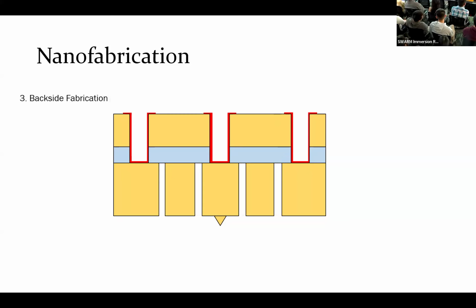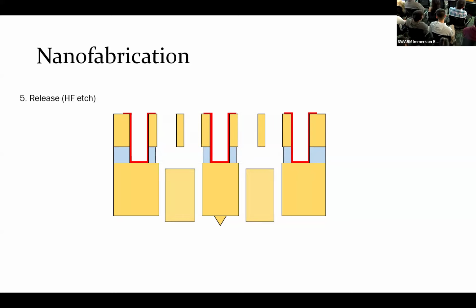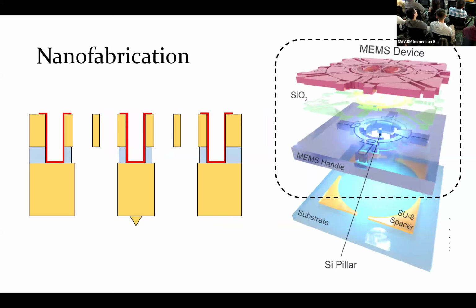And then we do the Bosch etching from the backside and also the top side, and then we release it using vapor HF. These constitute the different layers as you see here, the device layer and the handle layer, and how the silicon pillar in the middle is used for putting down the 2D material.